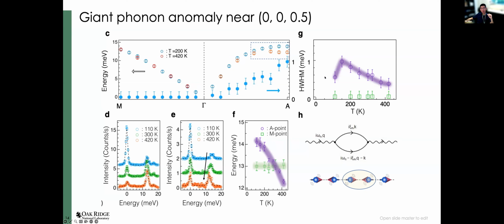At the same time, you can monitor the phonon linewidth, and again, the M point shows no broadening effect within our resolving power. But if you check the linewidth of the half L peak phonon, then you do see a pronounced enhancement of the phonon linewidth. And once you enter the CDW phase, the width gets narrower again.